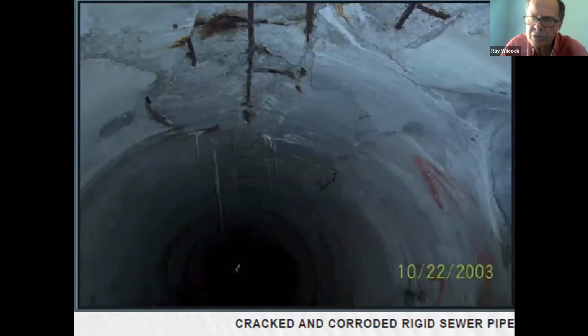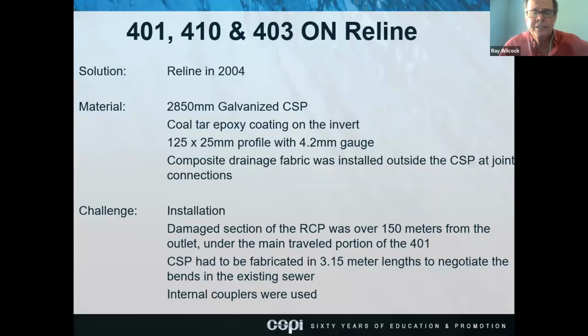Here's a picture back in 2003 of the concrete storm sewer. The salt had basically leached down from up above, obviously perforated, got into the rebar, and started cracking and corroding and so forth. So we were called in. We relined it in 2004. We used a 2850 millimeter galvanized corrugated steel pipe. We used coal tar epoxy coating on the invert. It was a 125 by 25 profile with a 4.2 millimeter thickness. And composite drainage fabric was installed outside the CSP at joint connections.